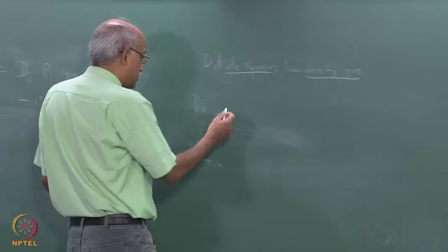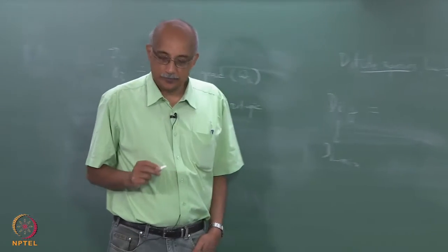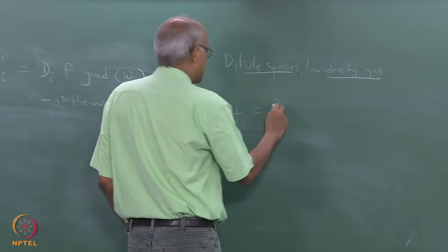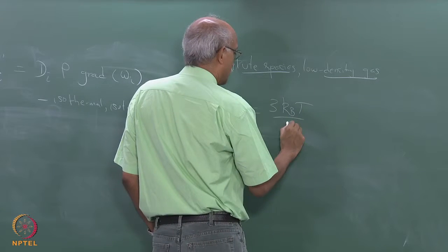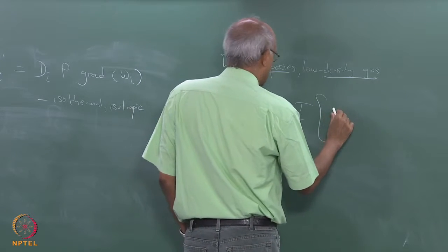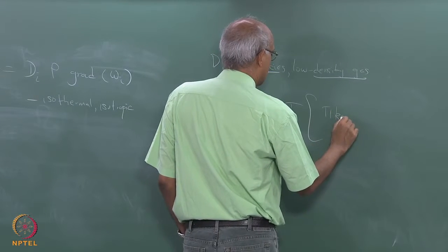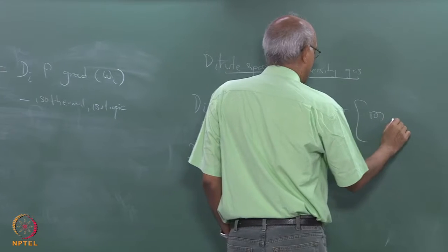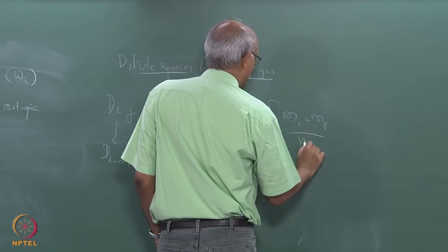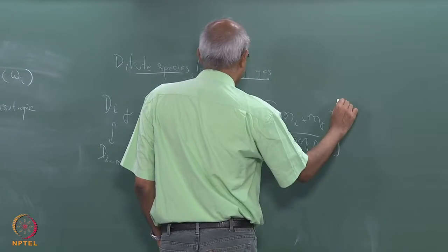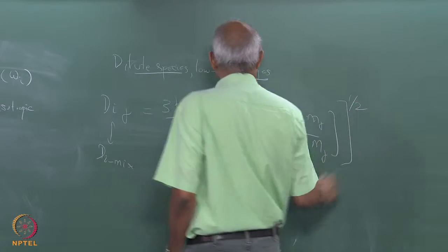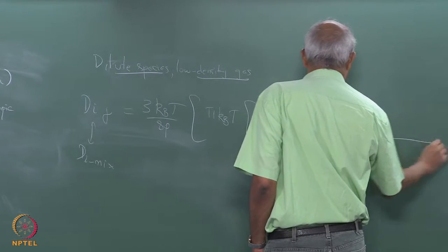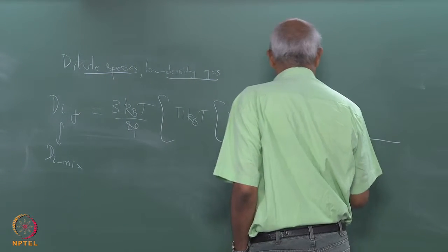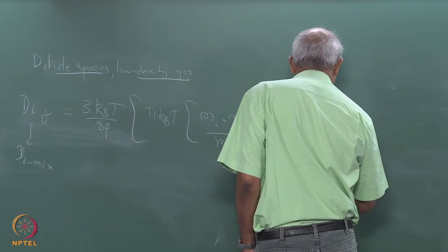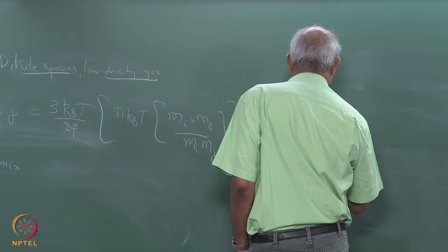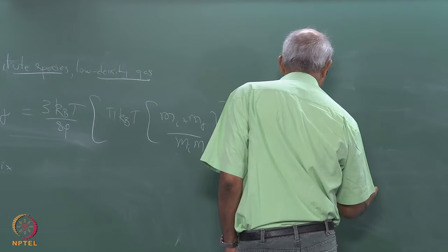So, there is an expression here for D_ij, which goes as 3 times k_B T over 8 p times (pi k_B T (m_i plus m_j) over m_i m_j) the whole thing to the power half, times 1 over pi sigma_ij squared omega_D, which is a function of k_B T over epsilon_D.